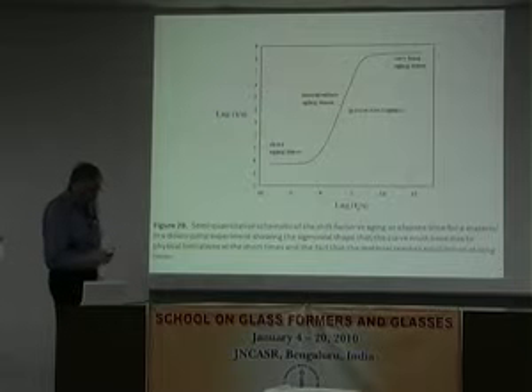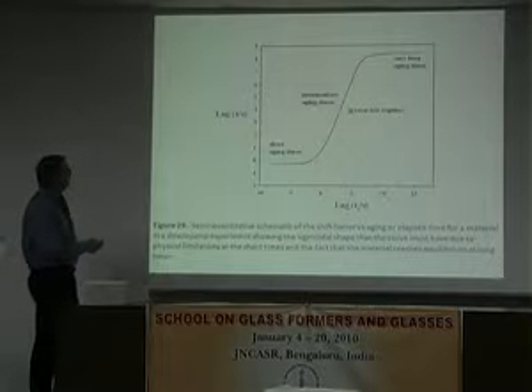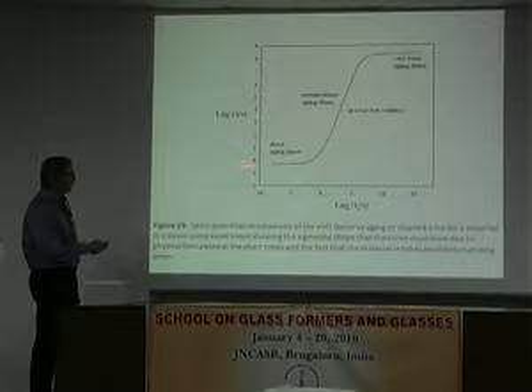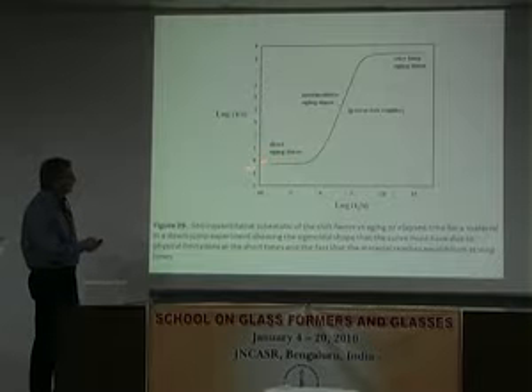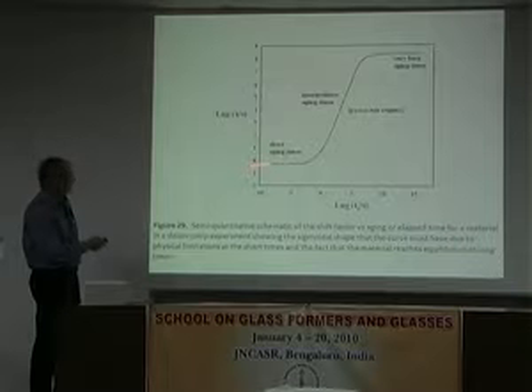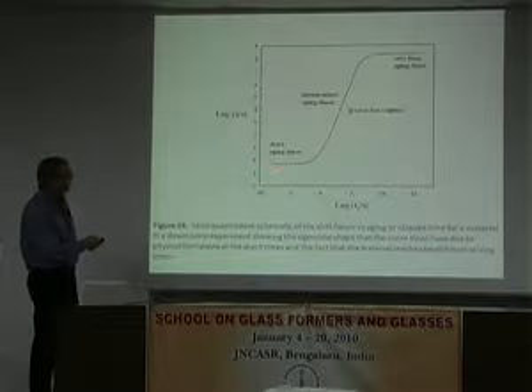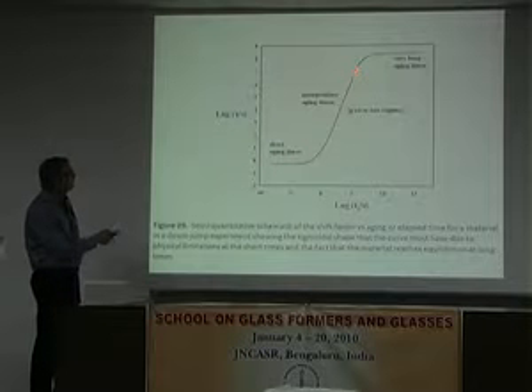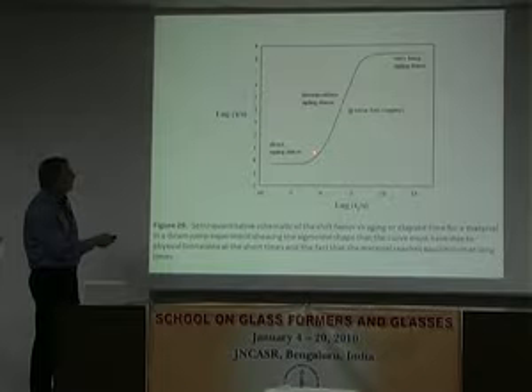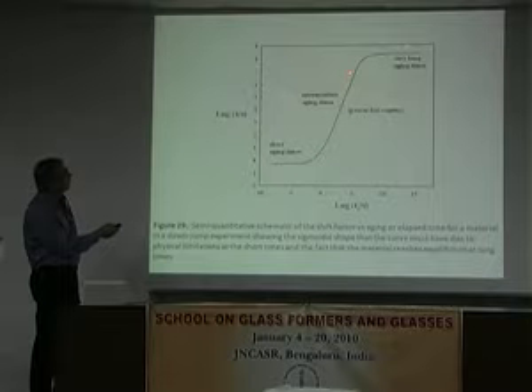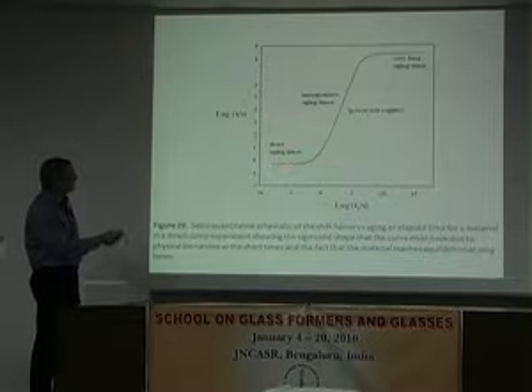And when I did that, just semi-quantitatively, you can see that you get a log of the relaxation time. You get a short one, and it's not going to age at all because it's going to be stuck for a while. And then we get into a power law regime. And then we know at very long times it's going to come over. So it really has this sigmoidal shape.